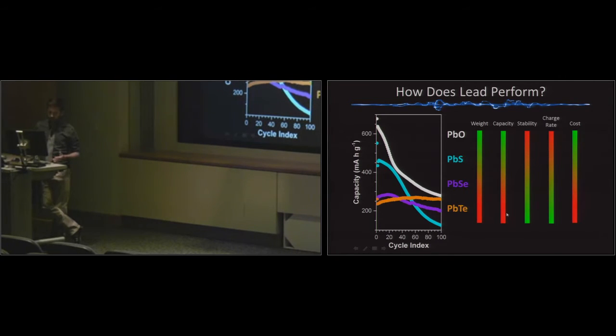In terms of stability, that trend reverses. The lead oxide has a really rapid decline in stability here in the beginning, and you can see it starts to flatten out as you go down the group in the periodic table, and then lead telluride itself is pretty stable over the 100 cycles that I tested. I don't show the data here, but in terms of charge rate, it follows the same trend where lead oxide can barely be charged at even a slow rate, and the lead telluride can actually be charged pretty quickly without losing much of its performance. I was able to get a battery to charge in about 30 minutes without losing much of its capacity at all.